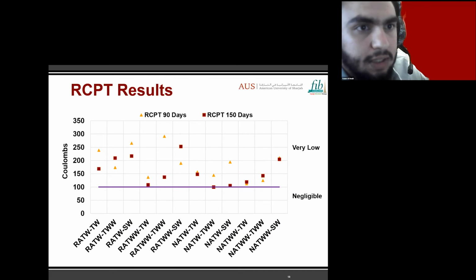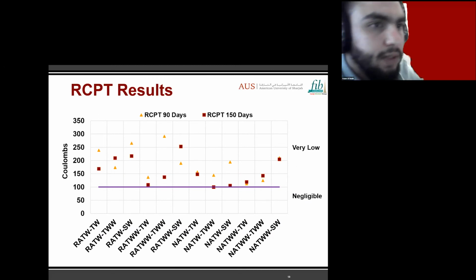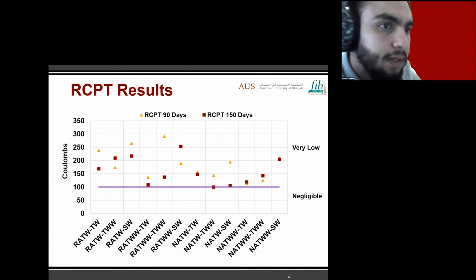From this figure, it can be better visualized where each test sample lies within the range provided by the ASTM standard, and it can be seen that all samples are within the very low region, and even very close to the negligible region.